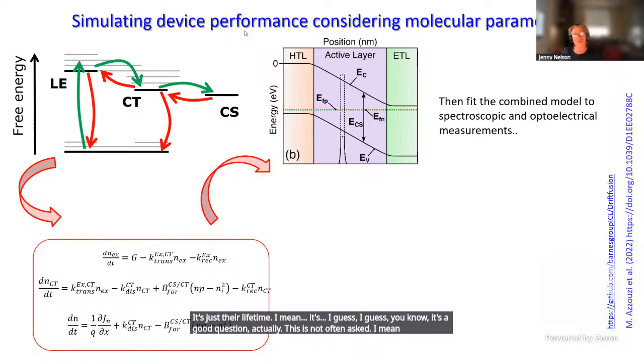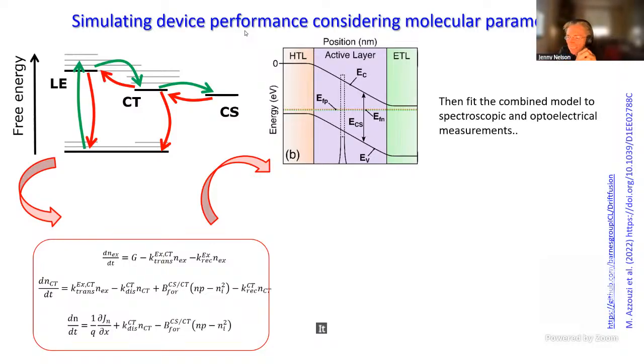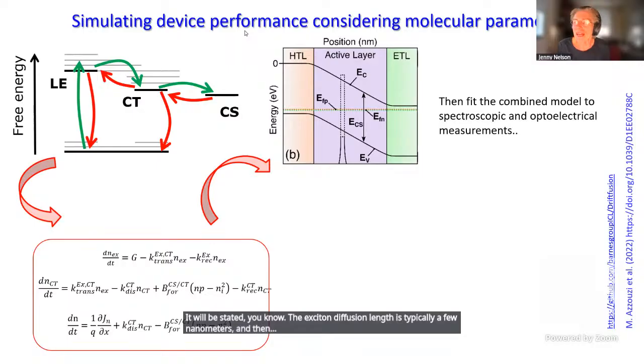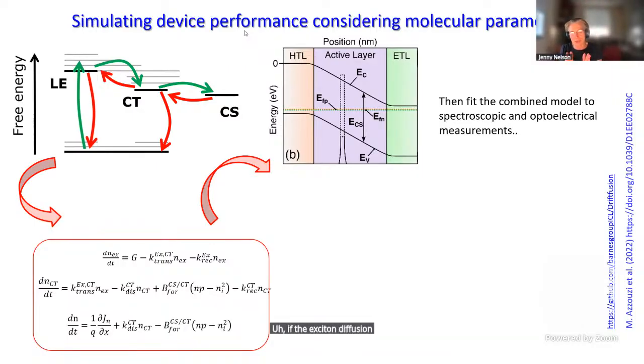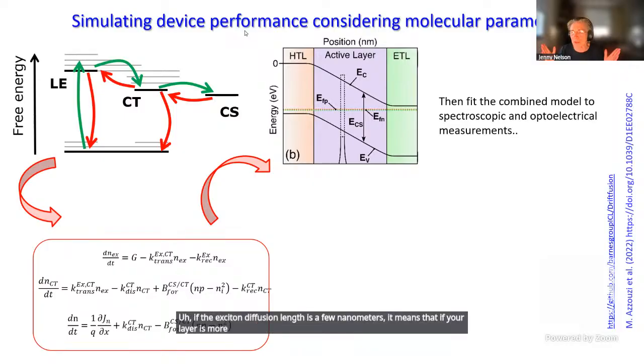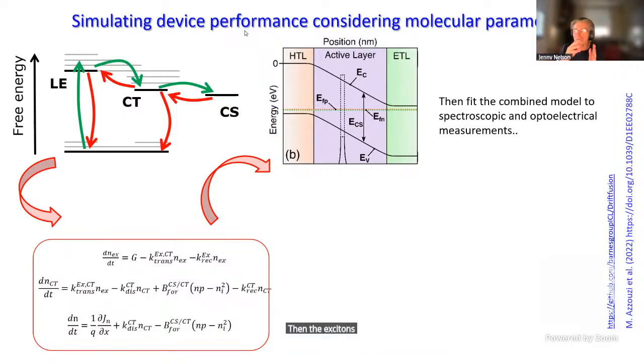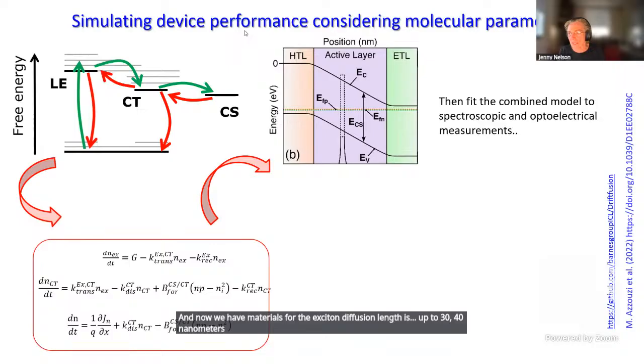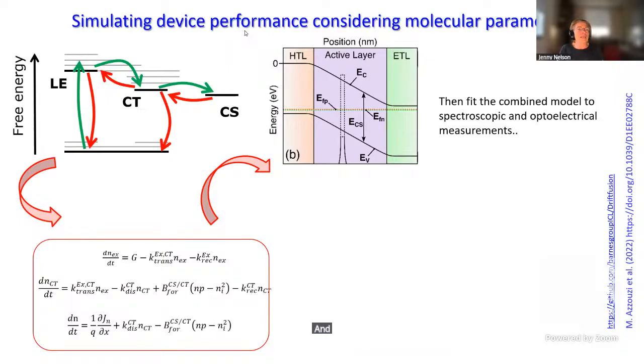So often it will be stated that the exciton diffusion length is typically a few nanometers, and if the exciton diffusion length is a few nanometers, it means that if your layer is more than a few nanometers thick, then the excitons will recombine before they can get to the other side and break up. And now we have materials where the exciton diffusion length is up to 30, 40 nanometers, and maybe that can increase. And the reason why the exciton diffusion length is increasing, I think, is due to a number of things.